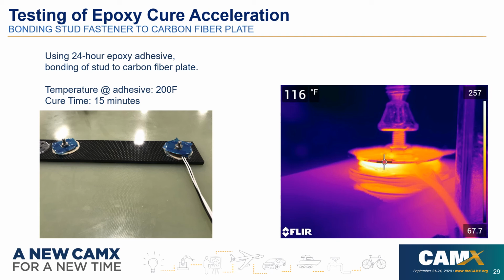Here we have a side-by-side baseline with no heat, and then we are using the serpentine heater here because we felt like the temperature from the thermocouple matched the surface temperature the best. On the right, you'll see the temperature of the blanket during the test. We did a 200 degree F hold, but for this one, we only did 15 minutes per the supplier recommendation for this epoxy. 15 minutes at 200 F was adequate for 100% cure.